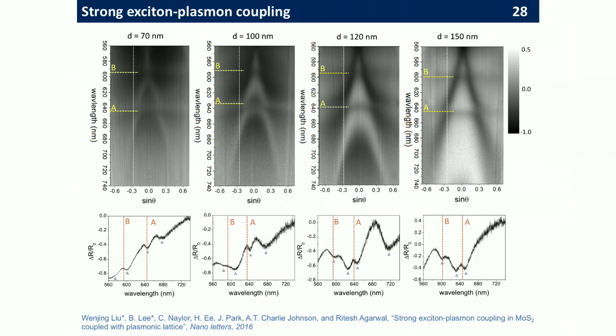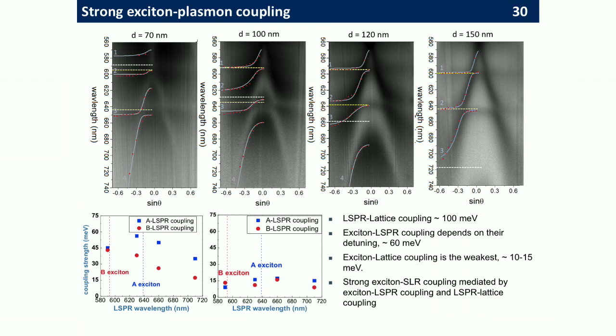Anyway, after many iterations we showed that we can get strong exciton-plasmon coupling in these systems. As you can see, these dark lines show the anti-crossing behavior between the exciton and the plasmon. If the coupling is weak, the dispersion of the exciton and the plasmon basically cross each other. But if it is strong, it shows this anti-crossing behavior. This was the original exciton line, and now in the hybrid system you create this anti-crossing behavior, and you can get these surface plasmon